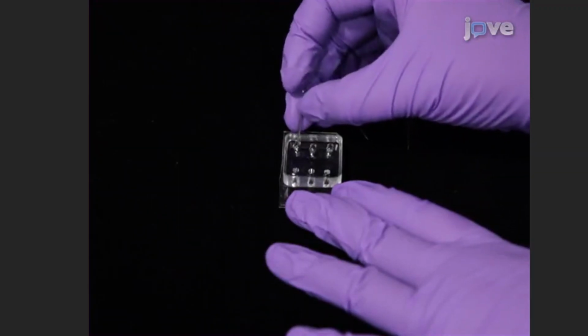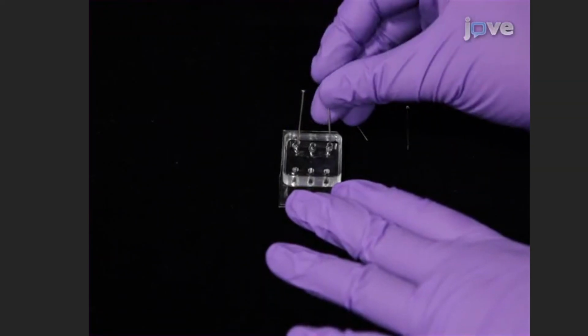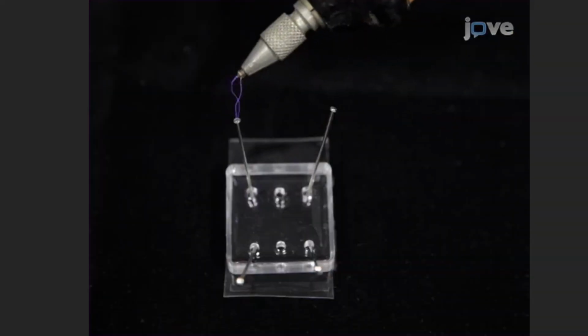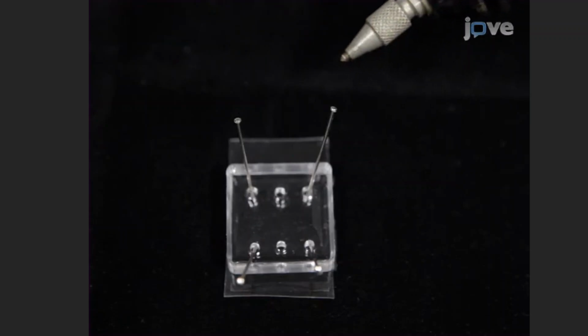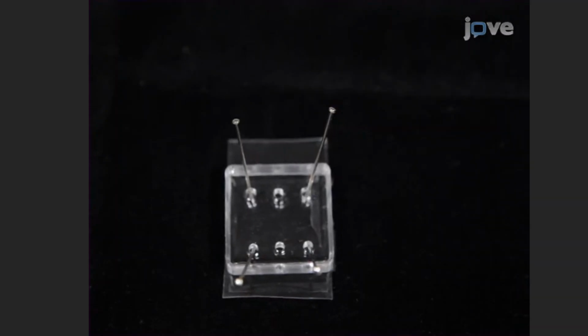Then, insert stainless steel pins into the ports for coupling the plasma generated by a handheld corona discharge generator into the vacant microfluidic channels. Point the tip of the plasma source close to the tip of one pin and plasma treat the microchannel for 1 second.